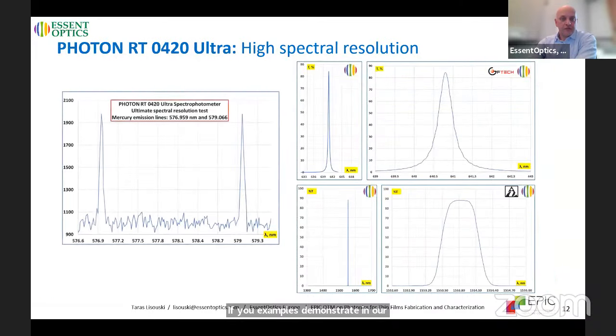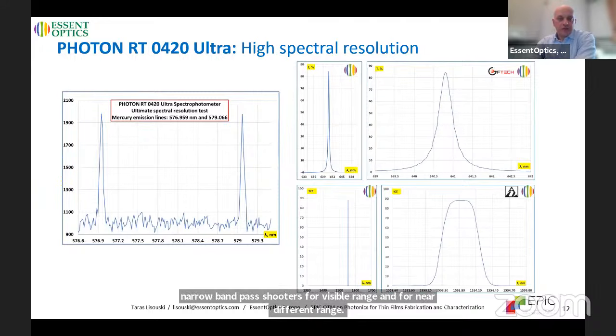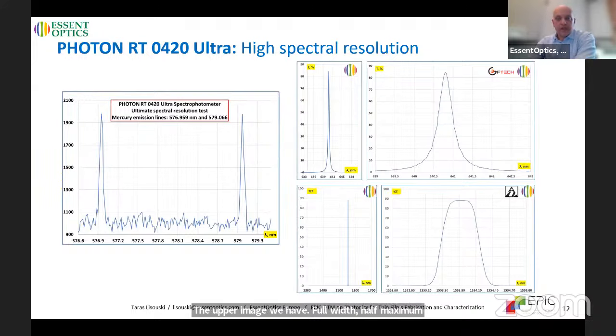A few examples demonstrating our recent results. The image on the left shows our capability to resolve mercury emission lines, which is a yellow doublet. And the images on the right show real measurements of ultra-narrow bandpass filters for the visible range and for the near infrared range. In the upper image, we have a full width at half maximum of 0.42 nanometers, and the filter in the image below has a full width at half maximum of 0.7 nanometers.